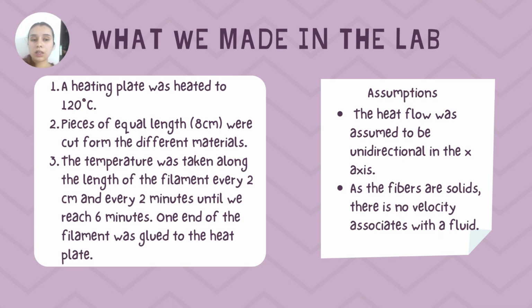With respect to the ease of data collection, this was not very simple with the laboratory equipment, which leads to possible errors in temperature measurement. There were major problems, particularly with the fiber that had polypropylene, as it melted quickly on contact with the plate, generating cuts in the fiber that can affect the heat flow. One way to make data collection easier could be to cut a longer length of the filament to make it easier to collect while using the thermometer to collect data.